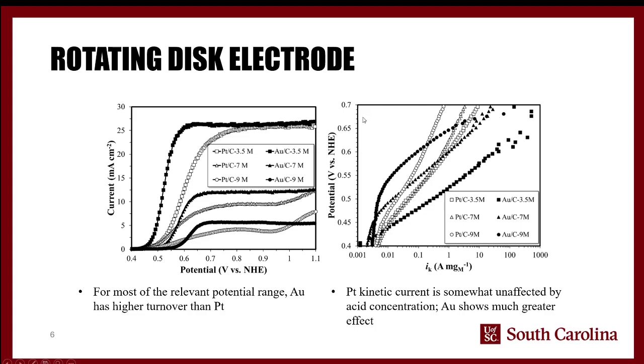The other big thing here is when you extract the kinetic currents, interestingly, the platinum kinetic currents, so the actual current due to the activity of the catalyst, is relatively unaffected by the concentration of the acid until you get to relatively high potentials. With the gold, on the other hand, there's a very clear difference between the three of them. And so the crossover where gold becomes better than platinum changes depending on the concentration. That was kind of an unexpected effect that's not necessarily apparent from the steady state current diagram, and it was something that was kind of interesting to see.